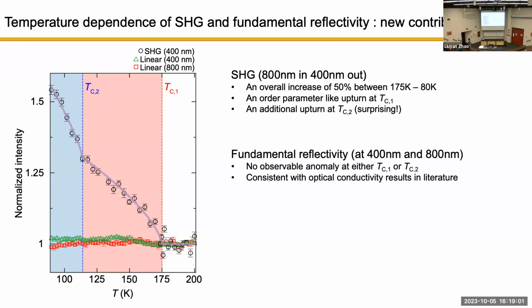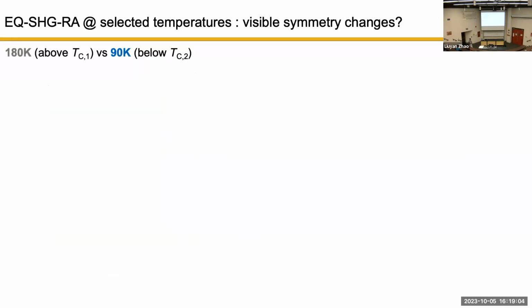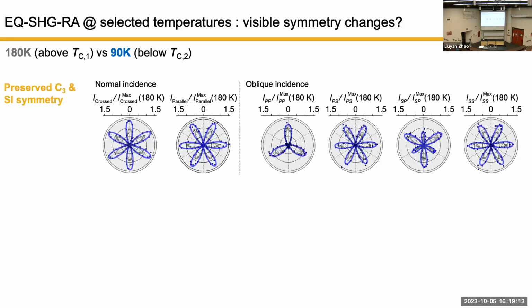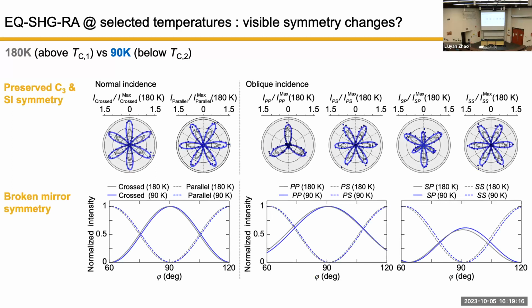So then we want to understand, what is SHG seeing here? We still do the same measurement. We take a flower pattern at high temperature, and we take a flower pattern at low temperature. That's our procedure. Here, the gray pattern is high temperature, the blue pattern is low temperature. What we see from the first line is that the blue pattern at low temperature becomes bigger. And if we look very carefully at the orientation, which we don't see in the polar plot but can see in this Cartesian plot, the blue pattern and the gray pattern are shifted a little bit in phase. The shift in the polar plot is essentially a rotation of the flower pattern.